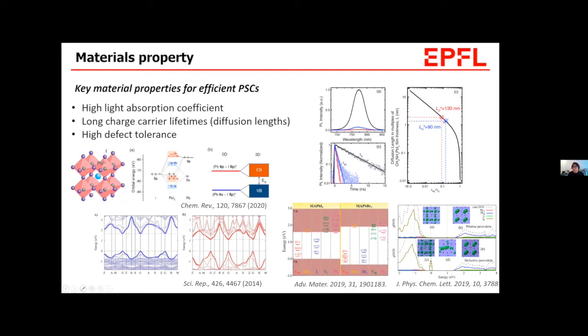When we see the simplest form, lead iodide, PbI2 here, they produce this overlapped orbital structure from their own orbitals, and it becomes the band structure when it comes to the crystal lattice in 3D. Again, regarding the origin of the high absorption coefficient, the optical transition type, direct transition or indirect transition, matters. Many theoretical calculations and experiments have proved that metal halide perovskite mainly has a direct band gap. Therefore, perovskite has a high absorption coefficient.